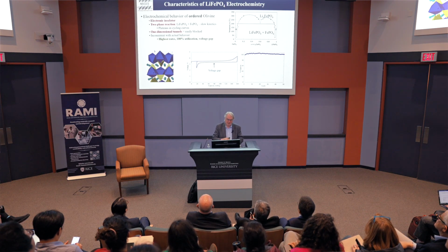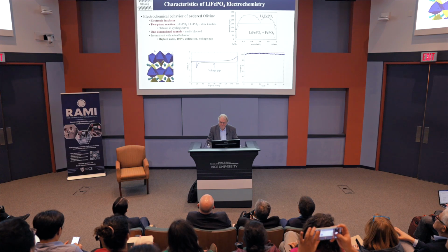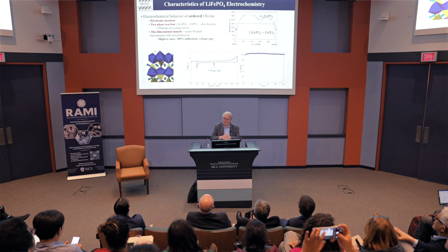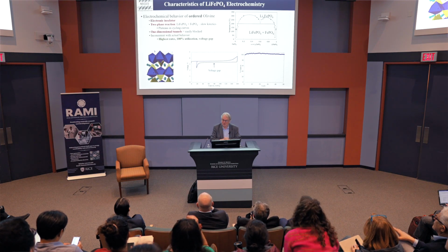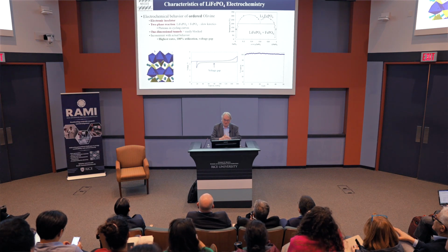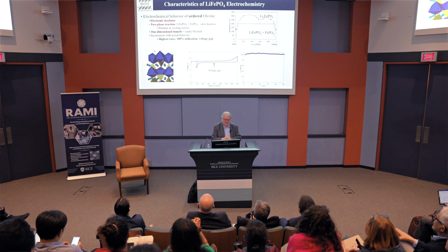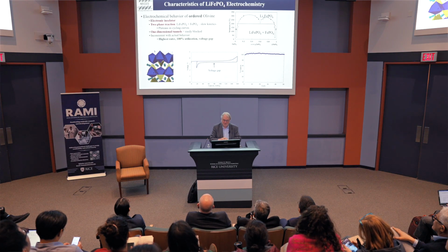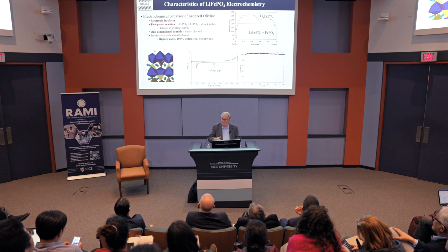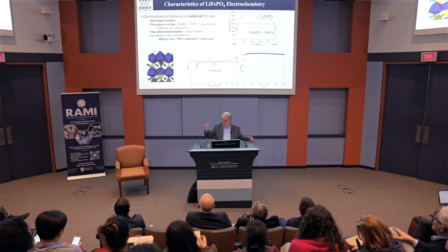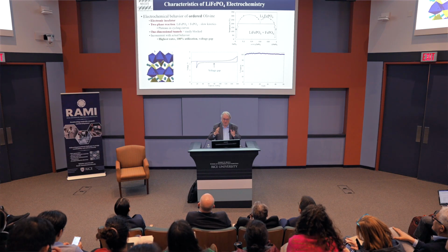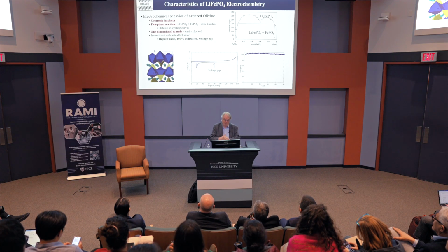So here is lithium iron phosphate. It shouldn't work. Phosphate's a great electronic insulator, so the electrons cannot get in and out. It's a tunnel structure, so those tunnels should get blocked. Okay, it's a two-phase reaction, unlike titanium disulfide or layered oxides, where you can change the lithium content continuously. It's just two-phase, so you have lithium iron phosphate and iron phosphate. You could argue you have to nucleate a new phase. That should make things worse. But it's totally inconsistent with the actual behavior. It's the highest rate. We can use all the material.